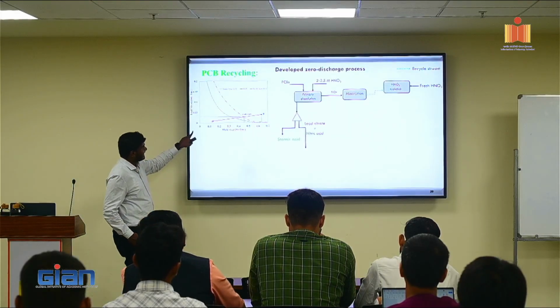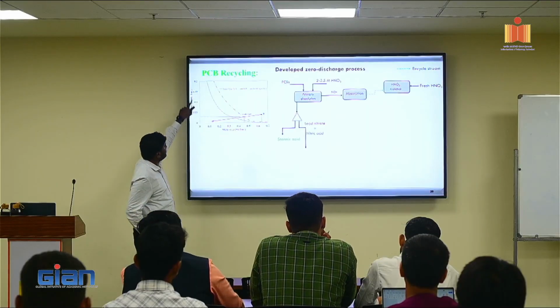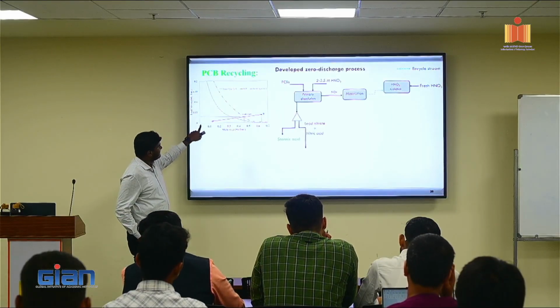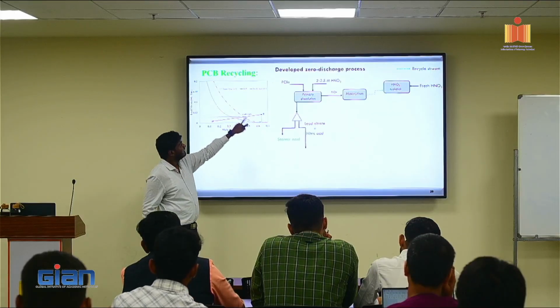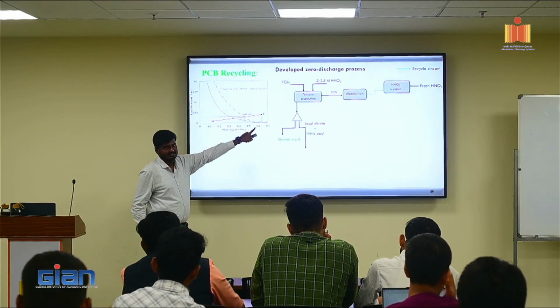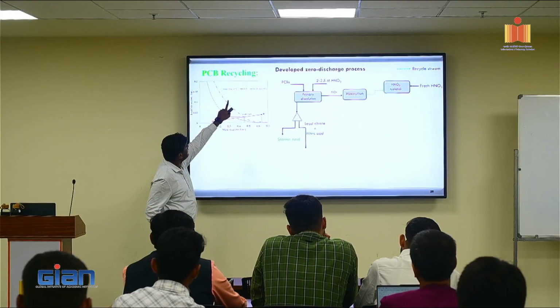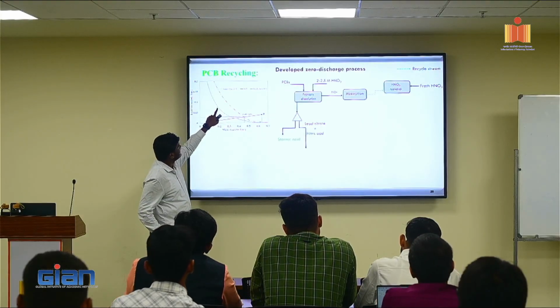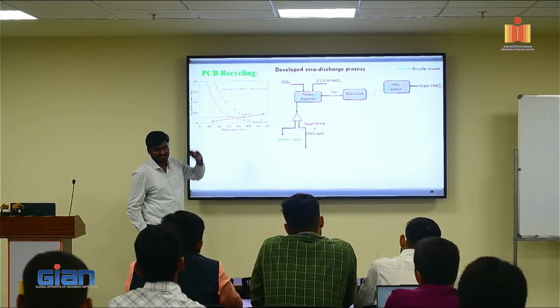So you have nitric acid on the x-axis and lead nitrate on the y-axis. You can see that with an increase in nitric acid concentration, the solubility of lead nitrate decreases. And I have shown it at two different temperatures. This is at 26 degrees centigrade and this is at 80 degrees centigrade.